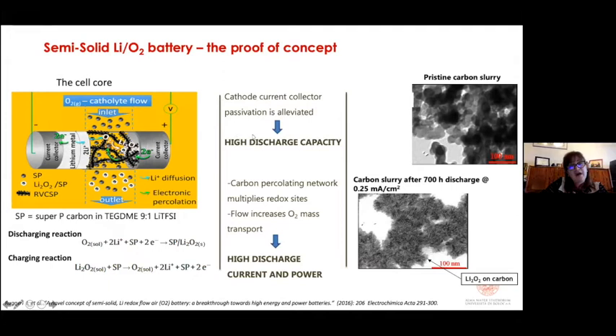This means that very high, impressive discharge capacity can be achieved. As an example, we were able to discharge this cell in 700 hours. And as you can see here in these TEM images, the peroxide was deposited as needles on the carbons and not on the current collector. Also, and that is important, the carbon percolating network makes this slurry conductive. And so it's like having multiple redox sites. The flow accelerates oxygen transport through the cell, and so increases the oxygen mass transport. And this enables us to achieve a very high discharge capacity compared to an air-breathing cell.